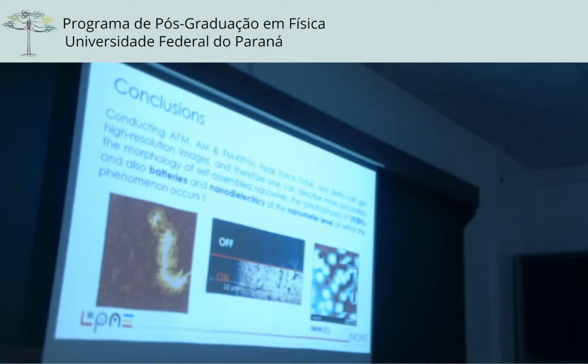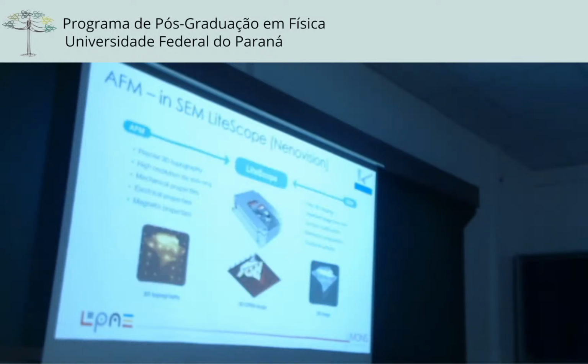This is, for instance, one example of photoablation of silver nanowires dispersed in a polystyrene matrix. And you have in red the polystyrene, the silver nanoparticle over there, and in blue we have the interface, which is extremely important in nanodielectrics to improve the properties of those nanocomposites.